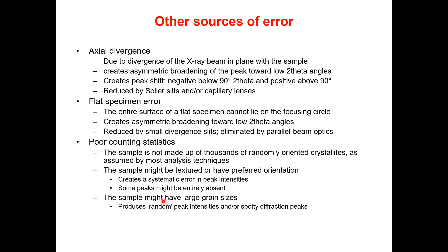If the sample has a grain size greater than 10 microns, which is considered a large grain size, this will produce random peak intensities or a spotty diffraction pattern in the XRD pattern.